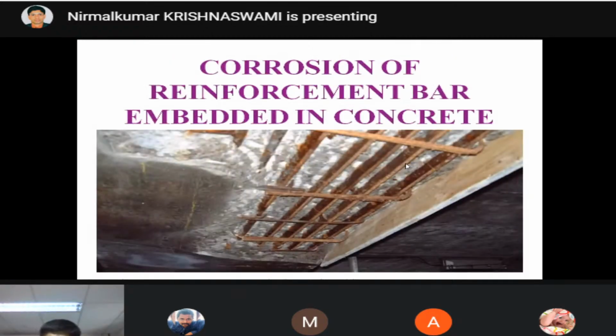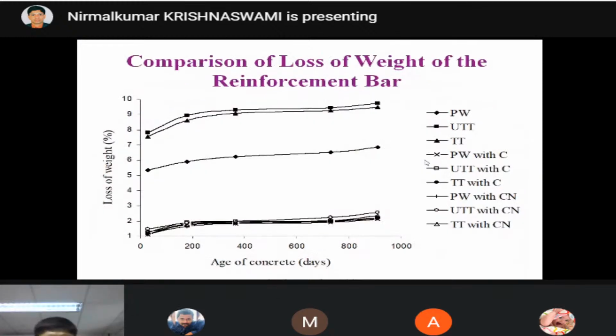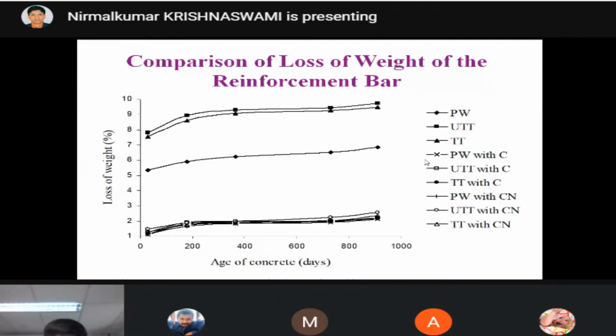Here what we did is we casted the lollipop test specimen for carrying out this corrosion. We took a cylinder of 15 centimeter diameter and 30 centimeter height, and inserted a 20 mm bar with a clear cover of 30 mm at the bottom. We passed the current and measured the current. At the end of 28 days, we stopped the experiment.